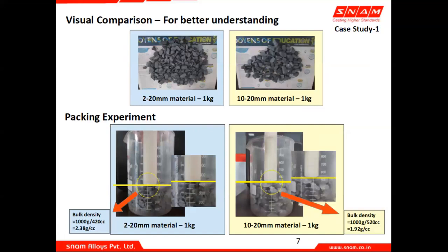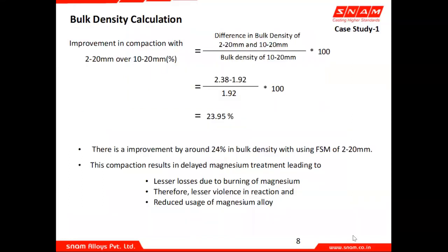So we took 1 kg of 2 to 20 and 1 kg of 10 to 20 mm. We put it in a beaker in the R&D lab, we filled it up, and we checked the bulk density with the reading, and this is what it occupied here, 420 and 520 cc. It occupied more in the narrow distribution but bigger size material. So roughly translating to a bulk density of 2.38 grams here, and it is 1.92, which is a 24% better compaction of the 2 to 20 wider distribution.